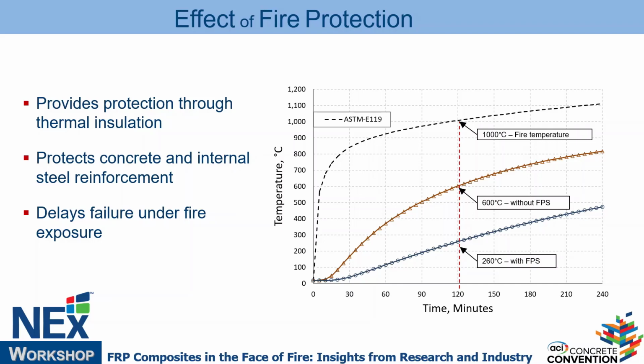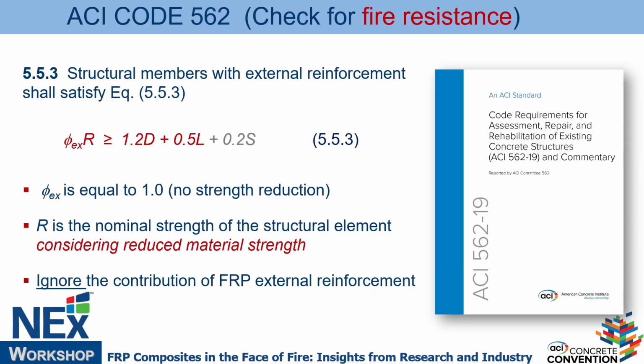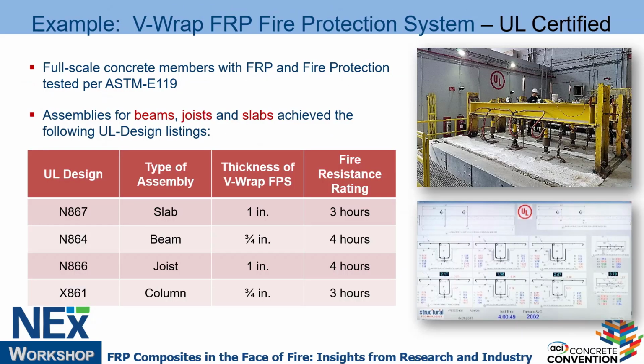And that's why with this system, you can see from most manufacturers, you can get almost up to 4 hours of fire rating. It does work, right? Because we're addressing the concept of protecting the elements. So what happened with this thing is, I'm basically increasing the nominal capacity during fire by protecting the steel and the concrete, right? And I have to keep in mind, even though I'm increasing the capacity, the demand may be increasing if I'm doing strengthening, right? So that's why I have to check both sides of this equation that we looked at, right?